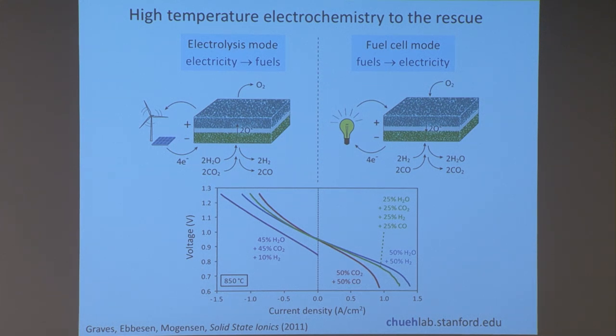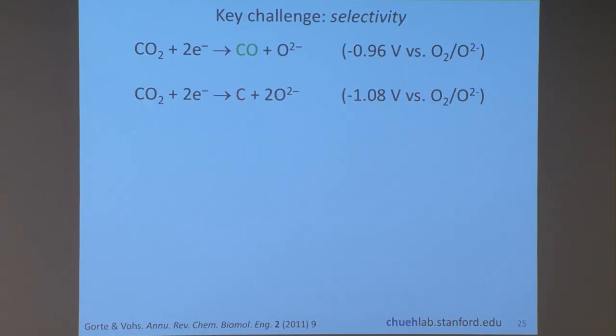You can do it with hydrogen, you can do it with water, you can do it with CO, you can do it with CO2. The temperature is quite high. This is the current challenge of the material set. It takes about 700 to 800 degrees Celsius to operate. But Bloom Energy, which was recently listed on NASDAQ, has been commercializing the right-hand side, the fuel cell. And I think the opportunity could be the electrolysis side to turn CO2 into CO. As I alluded to earlier, the challenge is selectivity.